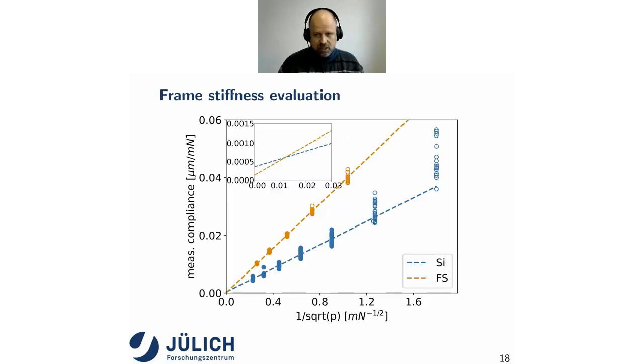And if we do that, in this case for silicon and fused silica, we see that here are our lines, and they should intersect the y-axis very close, but not at the origin. And if we zoom into that origin, we see, yes, the lines even intersect, but they definitely don't reach the y-axis at the same point. And that's what I really want to drive home here, is that the frame stiffness evaluation, which is the intersection of the blue line with the y-axis, is not constant. So different materials will lead to different intersection points just because you have mounted them slightly differently.